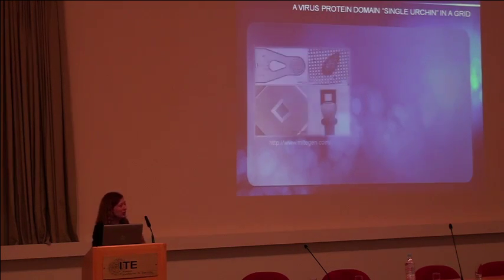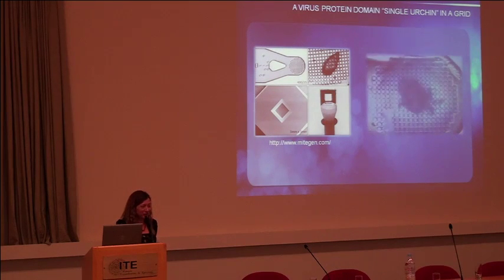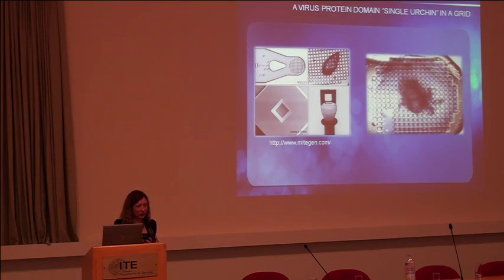The main complaint we were getting from biologists preparing samples was that we were requesting too large sample amounts. We needed four glass capillaries from 20 microliters to 100 microliters protein precipitate, and therefore we were obliged to reduce this sample amount which is required. So one night at the synchrotron we thought, why not follow the single crystal approach?